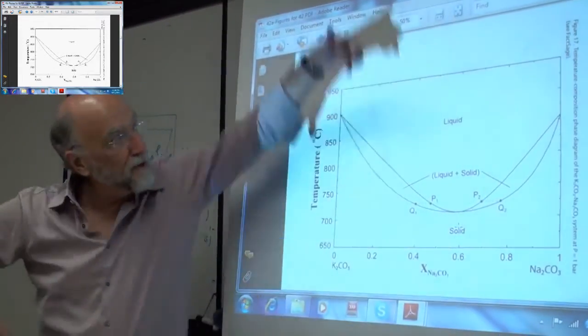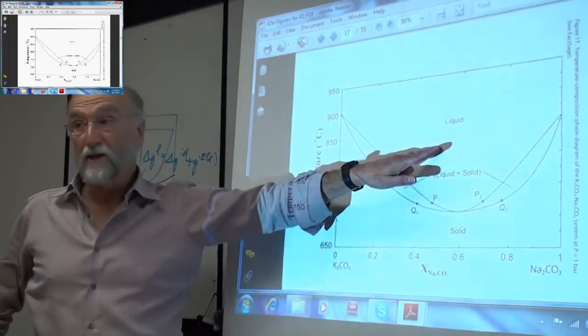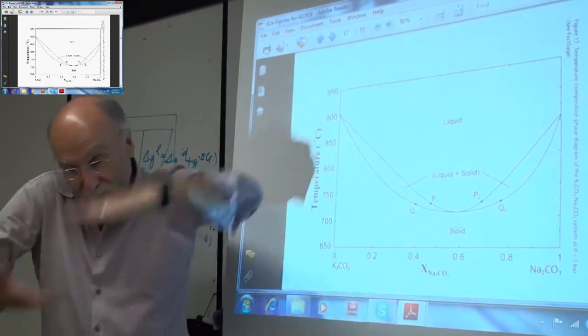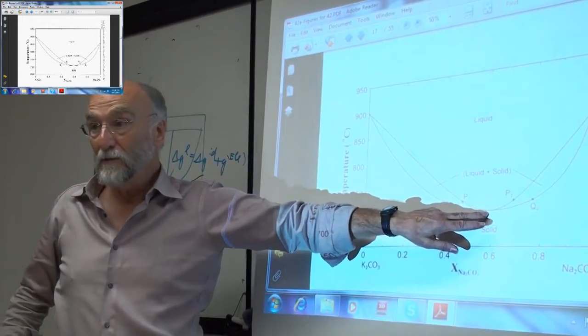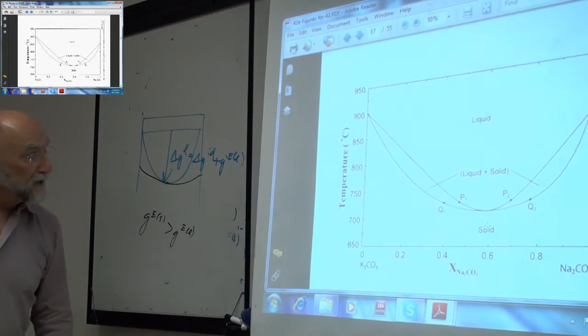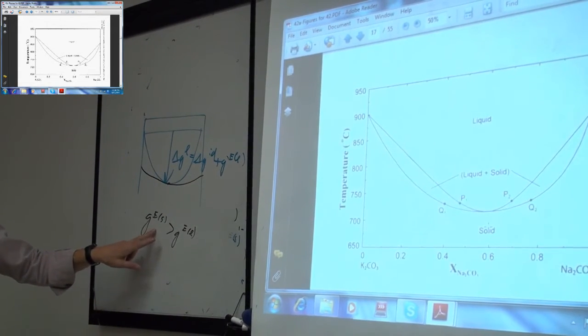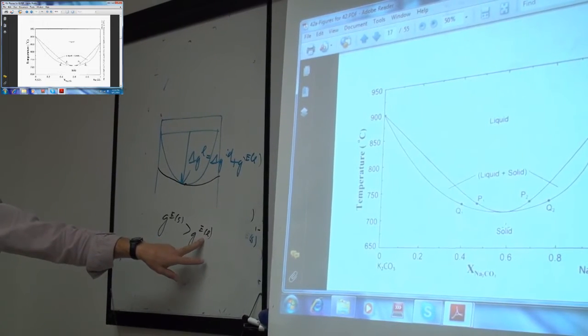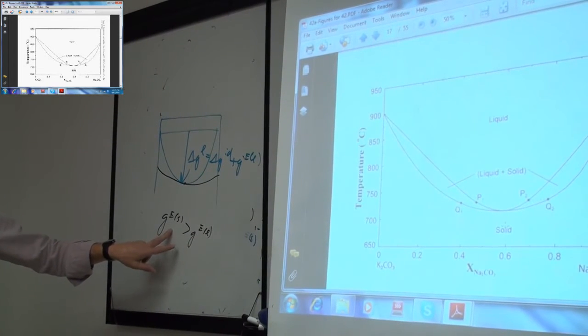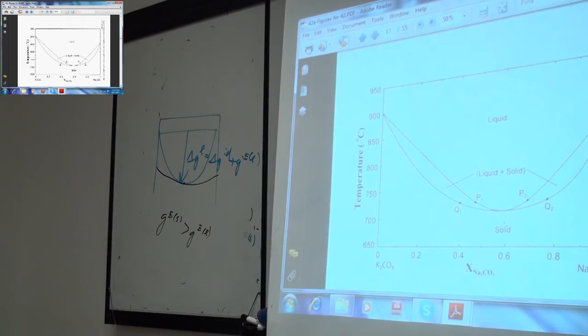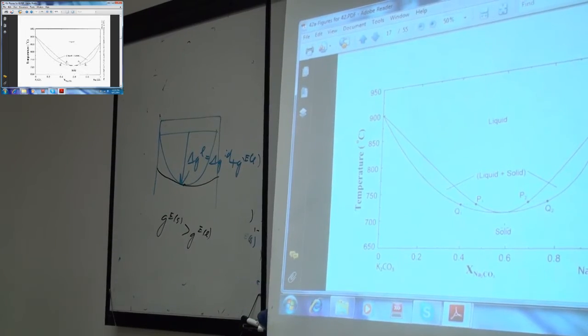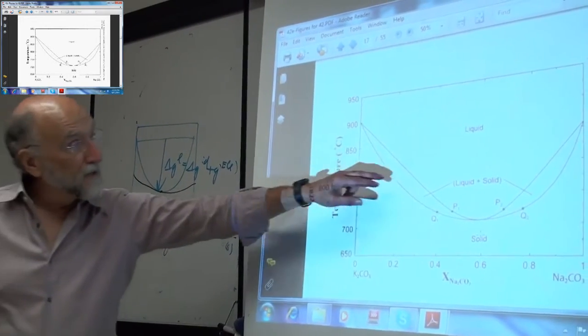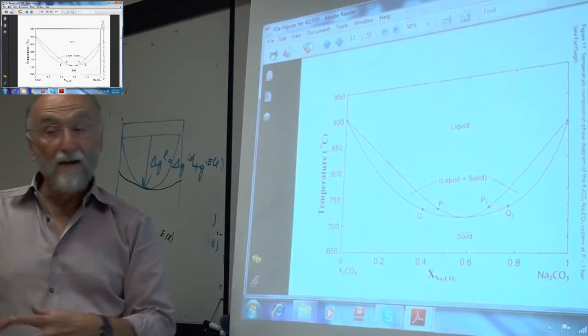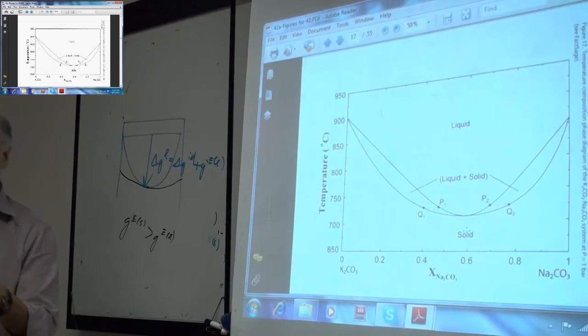You're taking this two-phase region and you're pushing it down, stabilizing the liquid. If you push it down enough, the thing will come together and you'll end up with a minimum. Now that could be because the solid has positive deviations or because the liquid has strong negative deviations. It's usually the former. If you have deviations in a solid phase and deviations in the liquid phase, the deviations in the solid phase would generally tend to be of the same sign, but more. So if the liquid has slightly positive deviations, the solid's going to have even more, simply because it's harder to pack things in together.